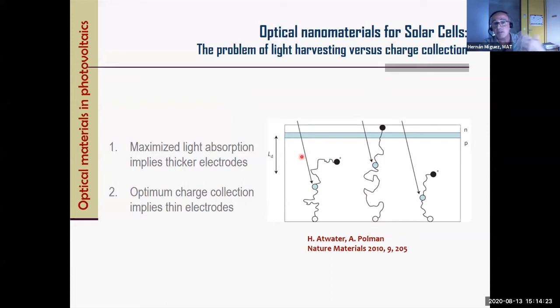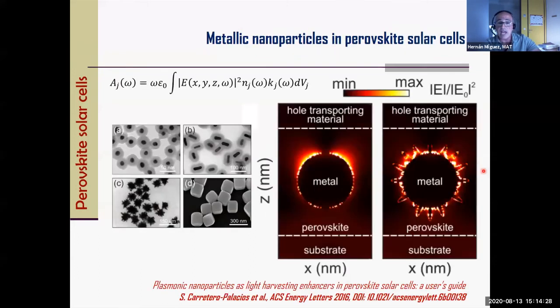So we had been playing around with this concept for a few years in other solar cells, and we applied the same concept to perovskite solar cells. We tried many things, which I'm not going to tell here today, but I will show you the example that I think is more promising. What you're looking at here is a simulation, because every time we start a project, we start simulating. What we did was to see the effect on the absorption of a thin film of perovskite, 200, no more than 300 nanometers thick,